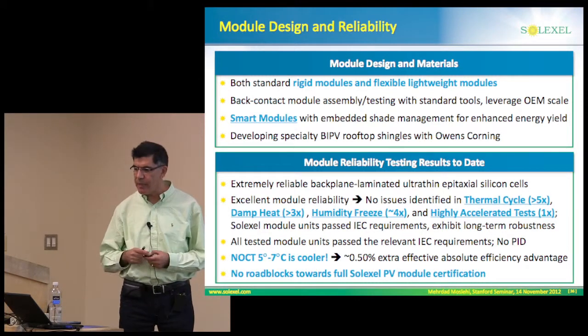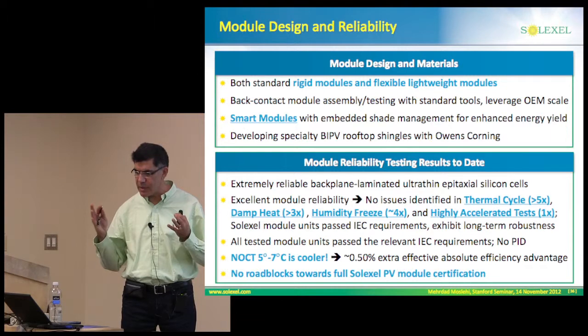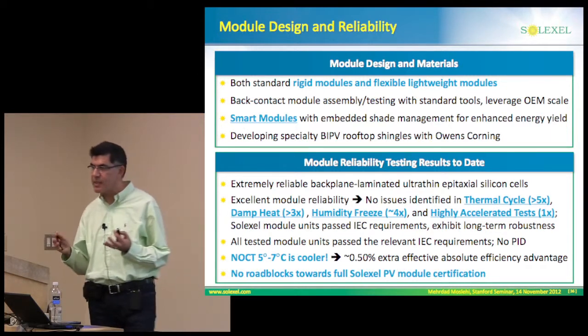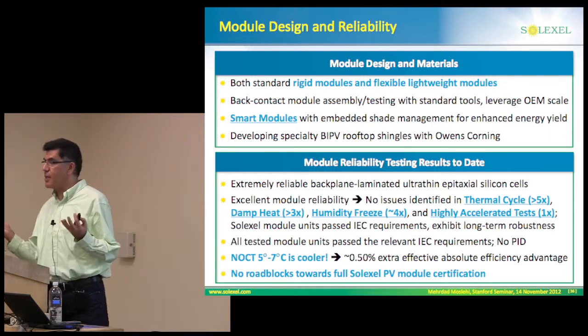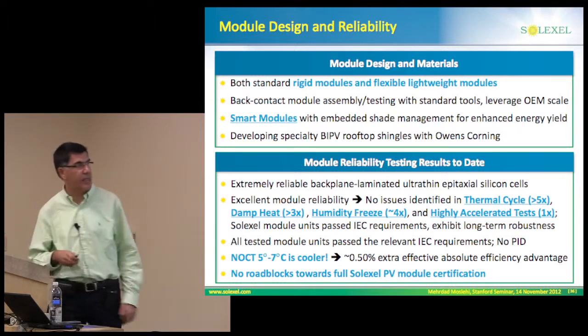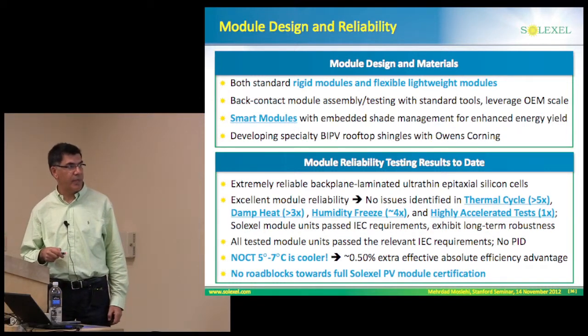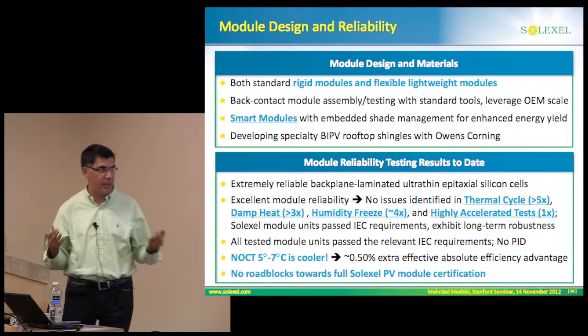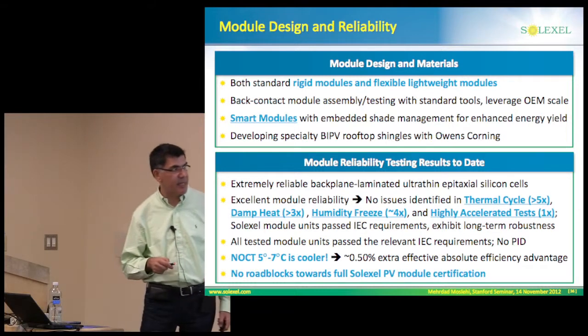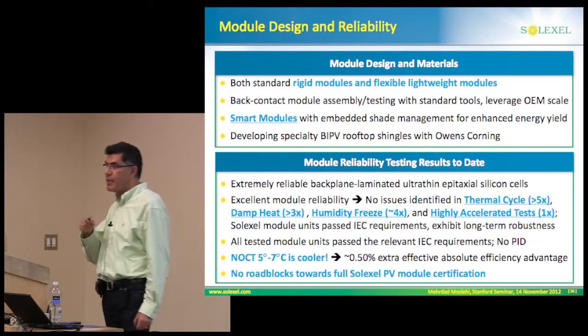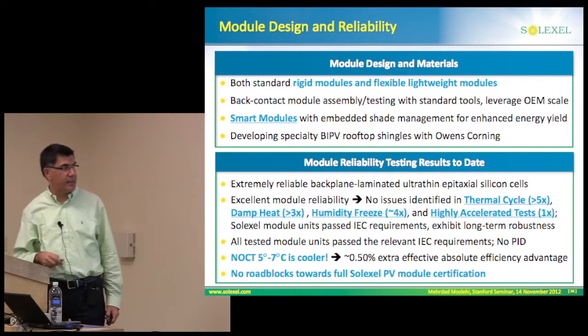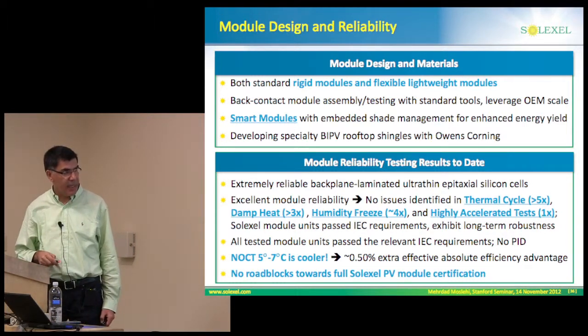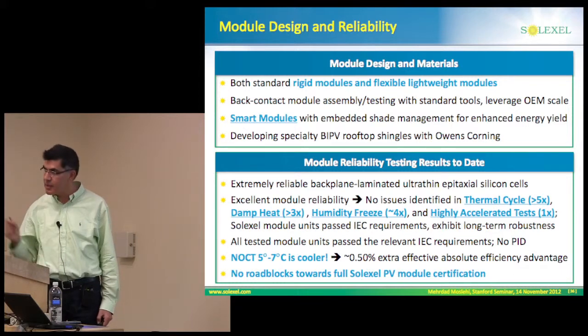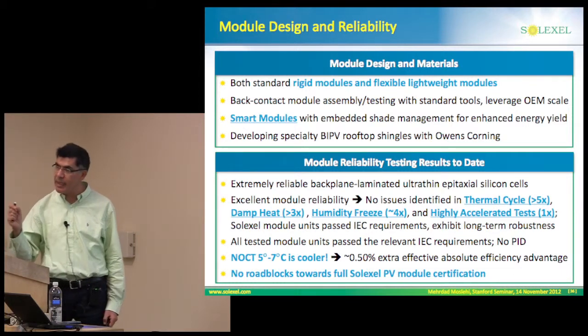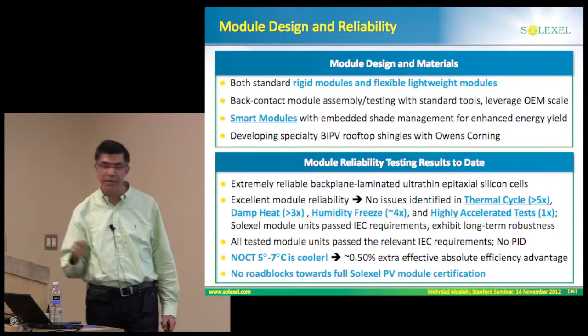We have done extensive reliability testing on our panels, and just to summarize that, what we have seen is excellent module reliability. Great thing is that it's crystalline silicon technology, no exotic material, and we haven't identified any issues with thermal cycling, damp heat, humidity freeze, and highly accelerated tests. Many of these actually had multiples of the IEC requirements. Another important test is so-called potential induced degradation, PID, and our panels don't show any PID effect.